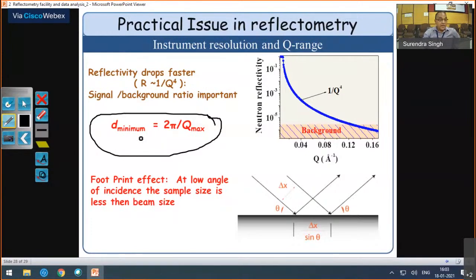So when you have a multi-layer, this is not right. But when you have a single layer deposited on a substrate, the minimum thickness for that single layer which we can study from our instrument is decided by the instrument's Q range, the Q maximum. Okay, so this is one factor.